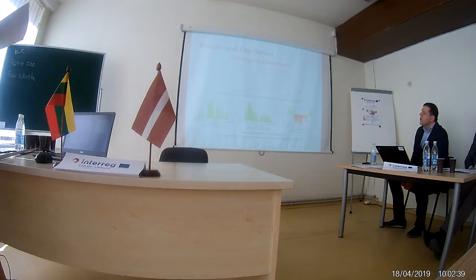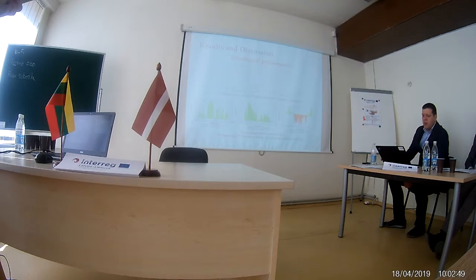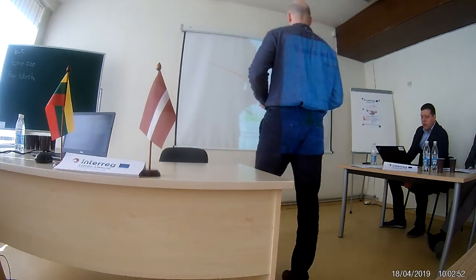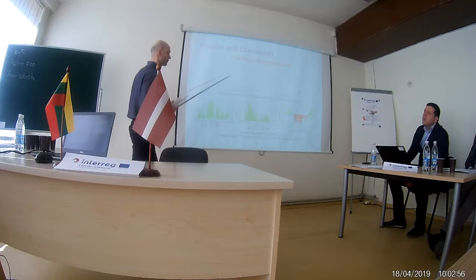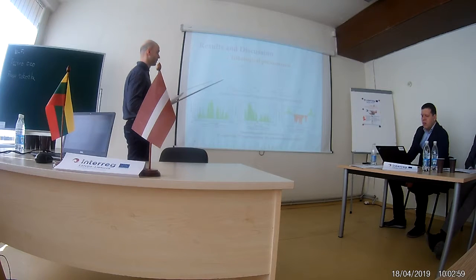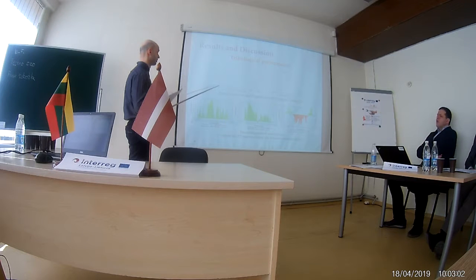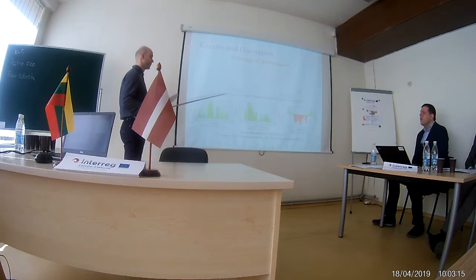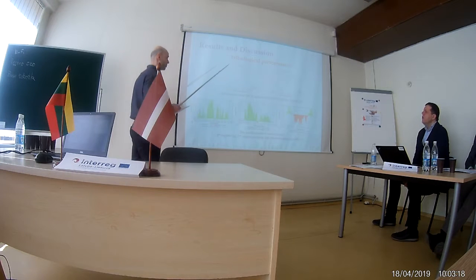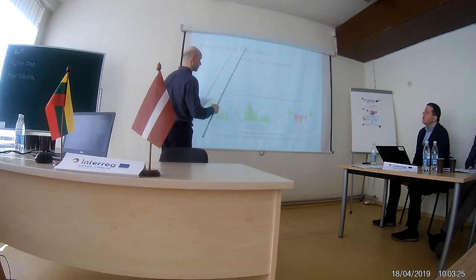As is well known, high hardness is often not the dominant factor to ensure the best tribological performance. Therefore, tribological analysis was fulfilled to define coefficients of friction and their distribution along the tests. So the average value of coefficients of 3 tests for both coating groups was very close, about 0.5. And there was a little difference for the second group coatings in the running-in stage.